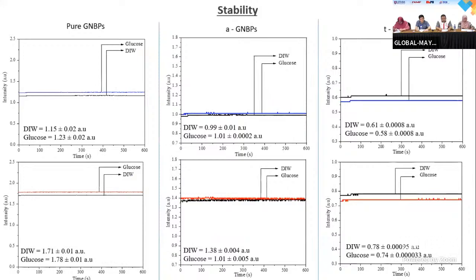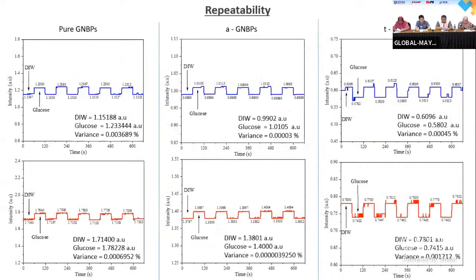Then the stability test is done to obtain the sensor ability when used at a specific time non-stop. In this study, I tested the sensor for 10 minutes non-stop because one spectrum can be created in 1 second. If we test for 10 minutes or 600 seconds, 600 data points are enough to test the system stability. The functionalization using amine and thiol can improve the stability, proved by lower error value. If we compare, t-GNBPs has a lower error value than a-GNBPs.